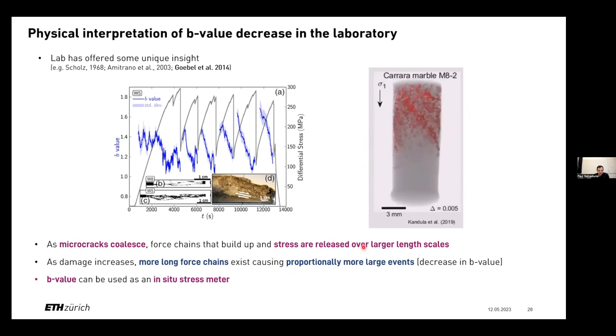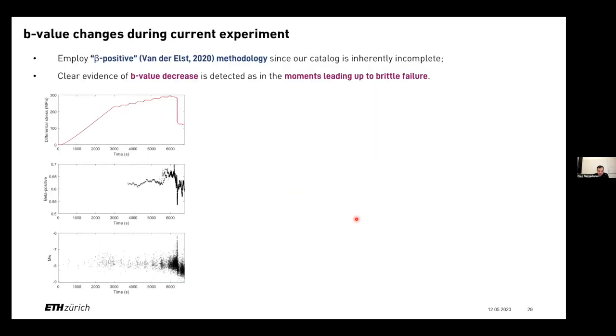These findings in many of these studies have been used to say that B value changes in nature can be used as in situ stress meters. This is something that was very useful and may still be useful moving forward. We want to move one step further with this as well. So what we're doing here is we're also evaluating the B value in the experiment that I just showed you. We employ the beta positive method, which is van der Elst's methodology that he's highlighted here. This is a method that should be used when your catalog is inherently incomplete, which most laboratory data sets are.